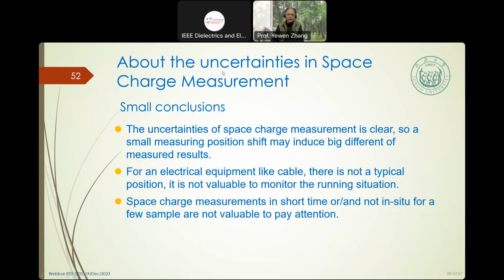So about the small conclusion, the uncertainties of the space charge measurement is clear. So a small measurement position shift may induce a bigger difference in the measurement. You move a little, maybe a big difference. For the electrical equipment like the cable, they are not a typical position, so it's not viable to monitor for running insulation. The space charge measurement in the short time or not in-situ for a few sample is not viable to pay attention and analyze.